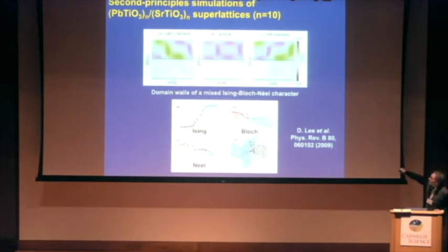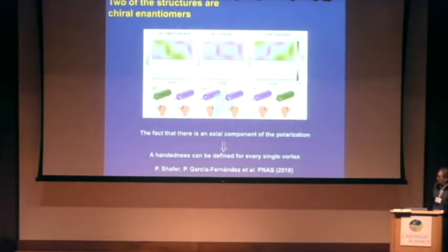So here, the domain walls show a mixed Ising character, so the polarization going from up to down, mixed with Néel, so this rotation of the polarization in the plane of the screen, combined also with some Bloch components where the polarization is just going out of the screen and coming back to it. So it's a mixture of the three of them. And the fact that we have also this axial component of the polarization makes the structures chiral.